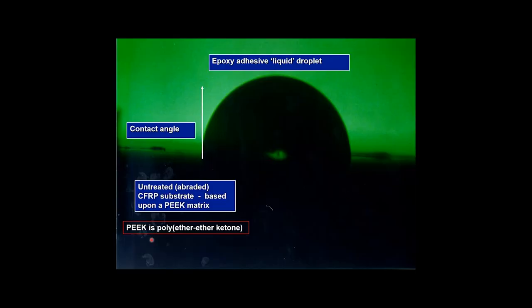Just to show the essence of the problem, it's not quite clear, this slide, I know, but here we have the surface of the PEEK CFRP. The surface has only been abraded, and therefore it's not a very good surface treatment. It's the one where the joint just broke open on the laboratory floor. Here's a small droplet of the adhesive. You can see it just sits there. It's sort of like oil on a non-stick frying pan. It's not wetting, it's not spreading. We can define a contact angle at this point here, and it's about 90 degrees. So we get very, very poor wetting indeed. And of course, the question that arises is how can you surface treat this material to give good wetting and good adhesion and bond it together for aerospace applications.